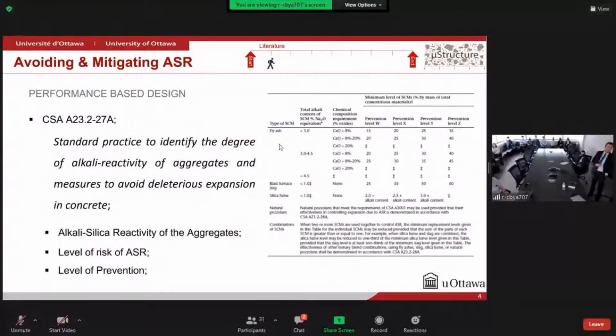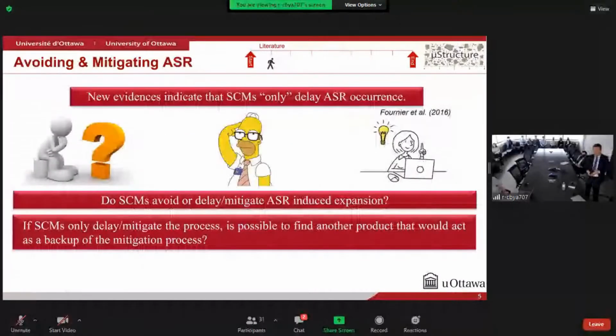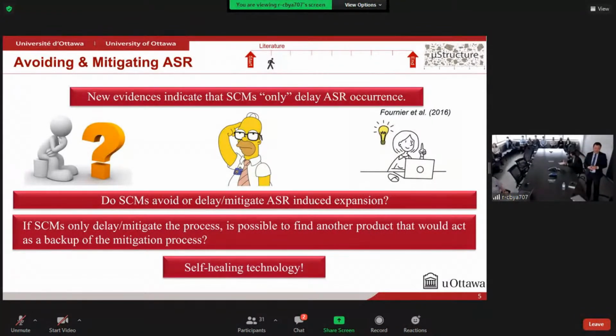However, new evidence in the literature indicates that SCMs only delay the occurrence of ASR in concrete. So we ask ourselves, do SCMs avoid or only delay ASR-induced expansion in concrete? And if SCMs only delay the process, is it possible to find other products that would act as a backup to mitigate the ASR development? So going through the literature with those questions in mind, we found that among the different alternatives, the self-healing technology might be the best option because this type of material can enhance the self-healing of the concrete and change the damage within the concrete.